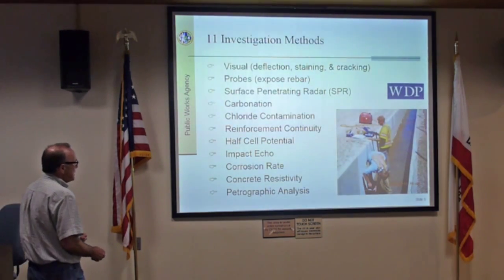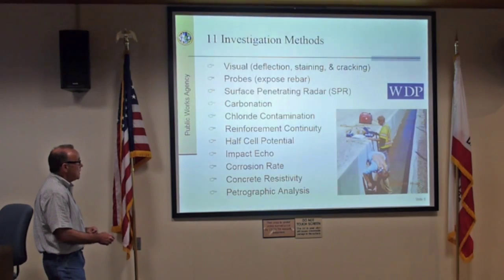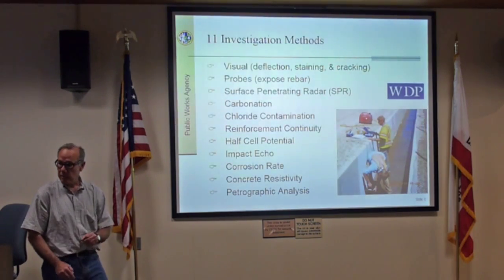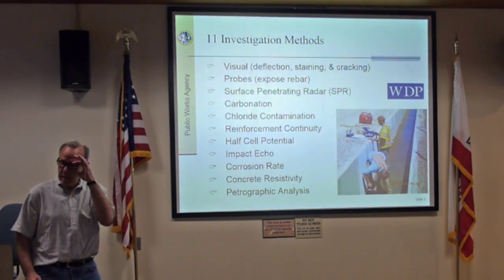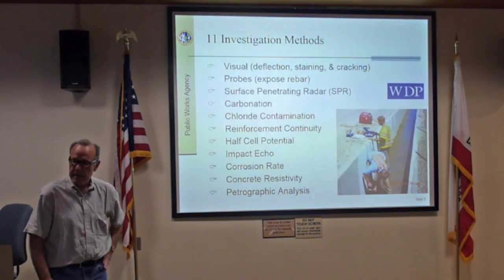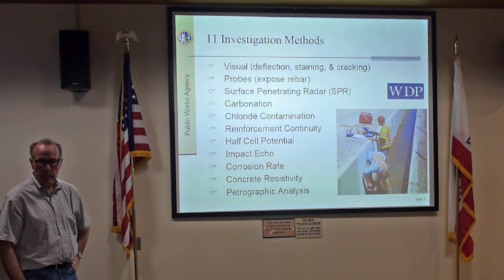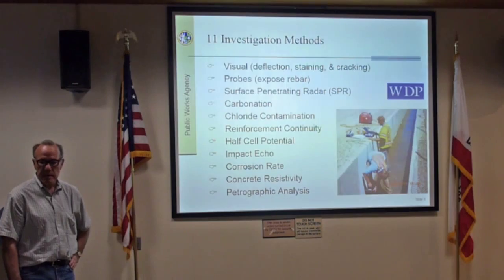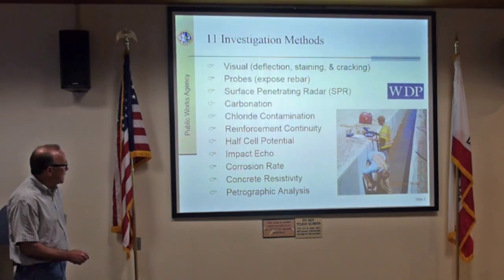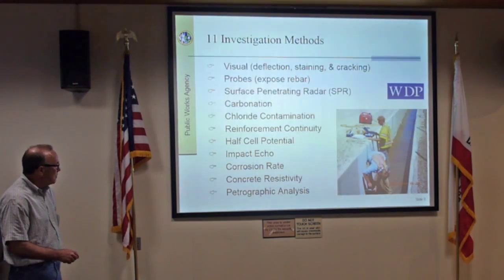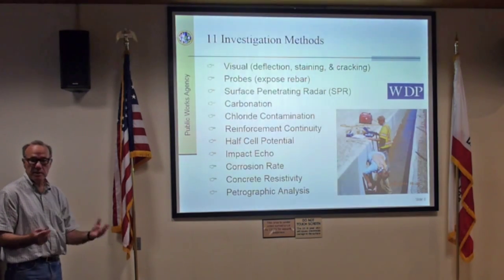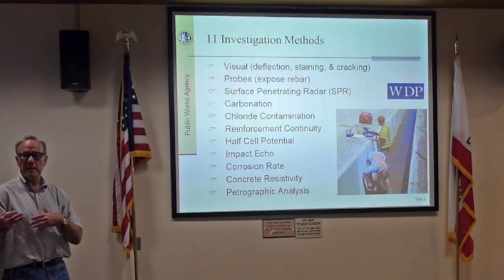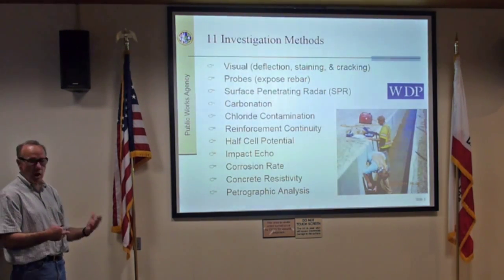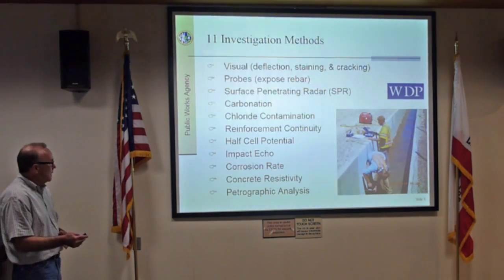The method that we typically use is the half-cell potential method, which was actually developed in California by a highway engineer named Robert Stratfull back in 1974, on a lot of bridge decks at Caltrans. It's a fairly simple method, and you're able to detect the presence of corrosion, but you can't tell anything about the rate of corrosion. So it helps, but it doesn't tell the whole story.